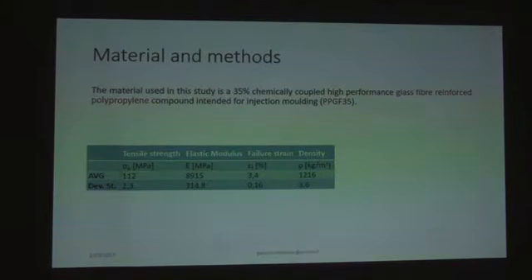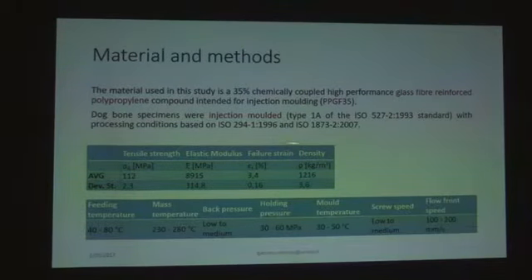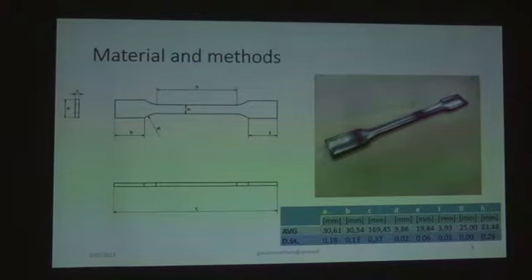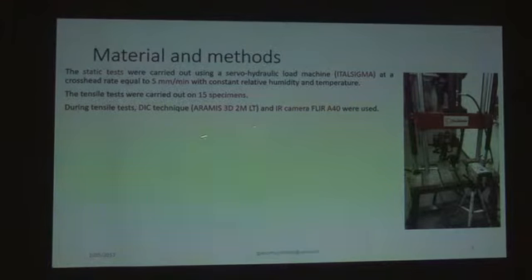The material used in this study is a glass fiber reinforced polypropylene. This is the mechanical parameters, and the specimens were injection molded with these parameters. This is the shape, and this is the geometry, the dimension of our shape. The tensile tests were carried out on a servo-hydraulic Italsigma machine at a cross rate of 5 millimeters per minute and on 15 specimens. During the test, we use the DIC technique and a FLIR camera.